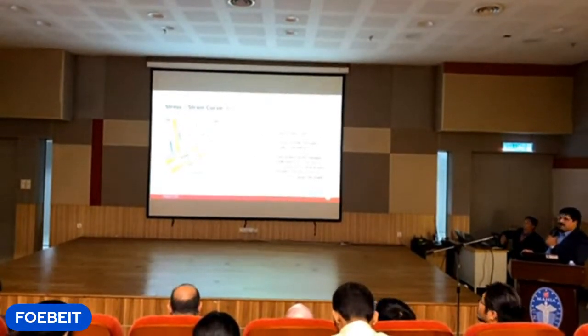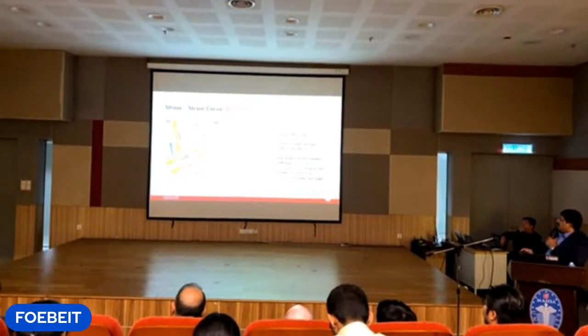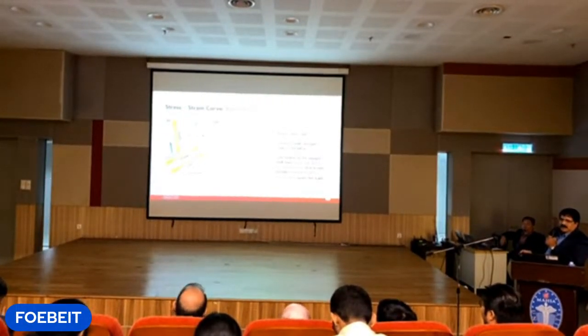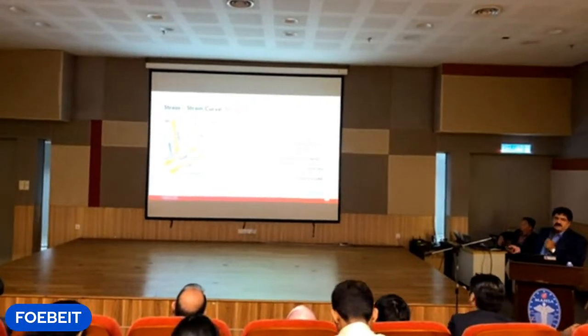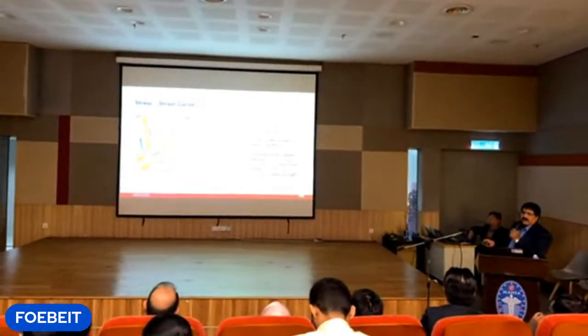So what is the effect of flat, on edge, and upright orientation on the 3D printed product? You see that the higher strength is in the on edge, the flat is lower, and upright is more brittle than the other two printing orientations. So each and every parameter is influencing the material behavior and also the nature of the material, whether it is more brittle or less brittle.